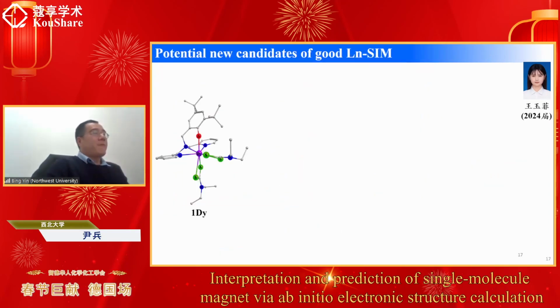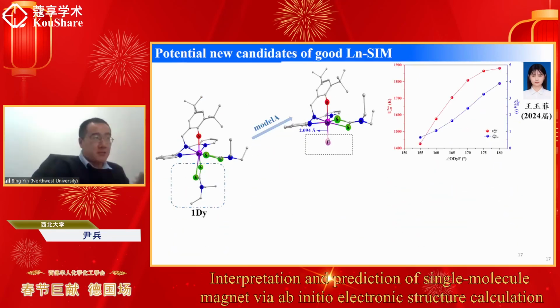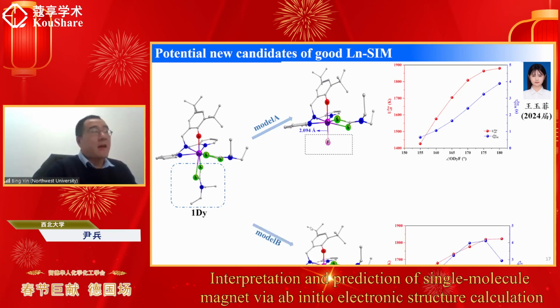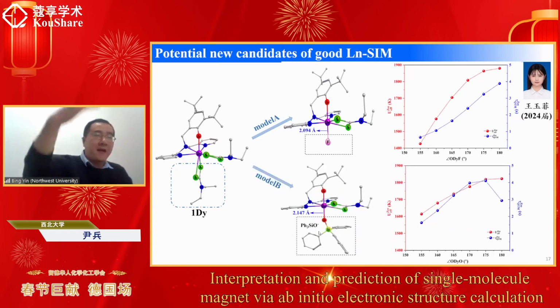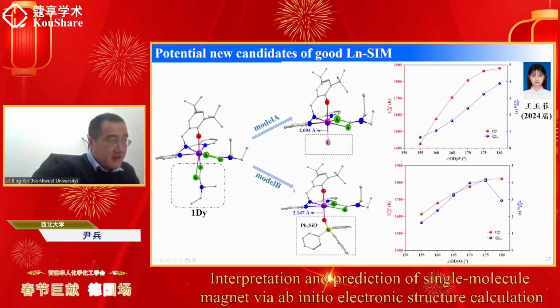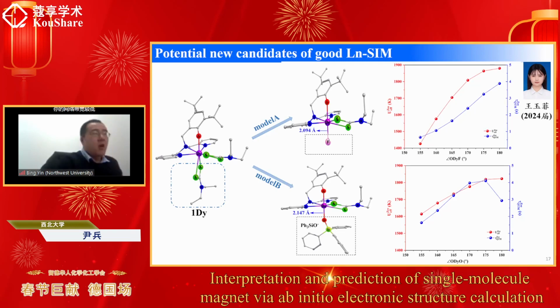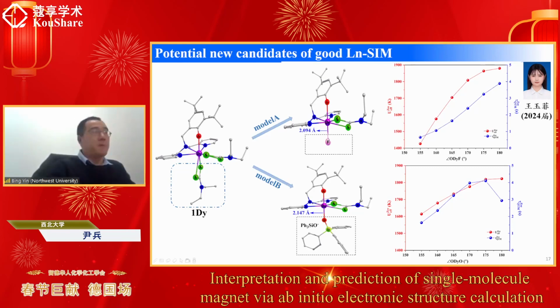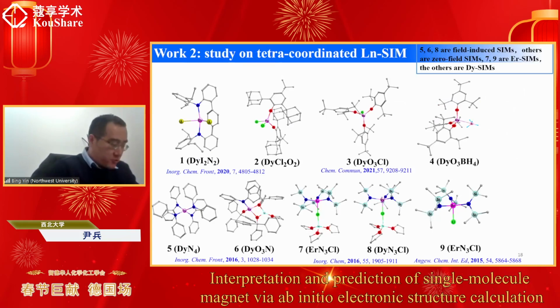And with this result, we have proposed some other new models which may show a better single molecular magnetic behavior. That is, we replace the axial sulfur coordination by some other atom, for example, a fluorine atom, or other ligand with an oxygen atom. And our calculations show that these proposed new models will have a higher energy barrier and longer QTM time compared with experimental systems. That means these two models have the potential of showing better single molecular magnetic performance than the system 1Dy, which has already been reported experimentally. And this is the first work I want to share here.